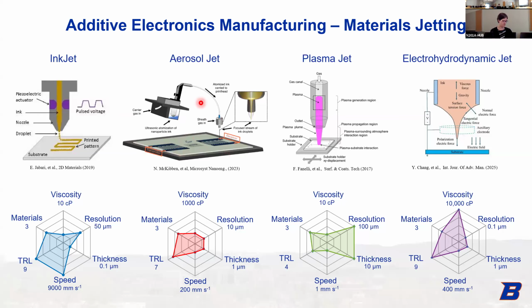The aerosol jet printer is a newer technology. In this case, you have your ink sitting in a glass vial. You put some energy through megasonication. That creates an aerosol right above. Your gas will come in, pick up those droplets, take it to the print head where a second gas comes in. This is the sheath gas, and focuses the beam. And so you can actually get a large laminar flow distance, about 3 to 5 millimeters or so. Gives you a good standoff, and so you can actually print conformally over 3D substrates with this. You get better resolution here. Inkjet's about 50 microns in lateral resolution. Aerosol jet, you can get down to about 10 microns.